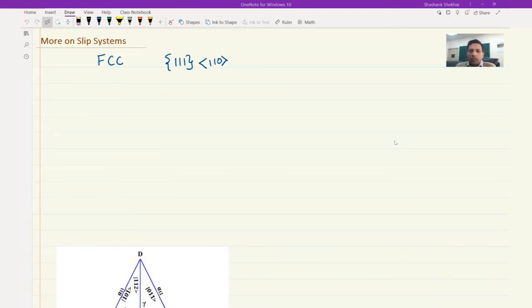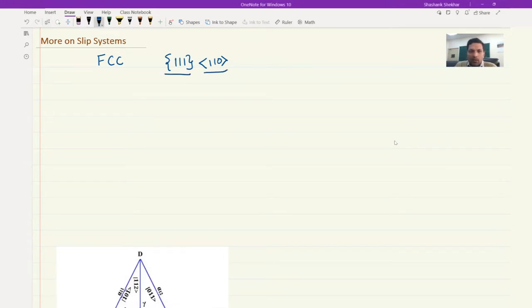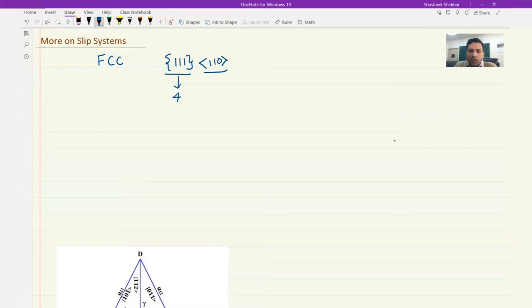We have looked at the various slip systems, now it's time to get familiarized with them. First, let's look at FCC. For FCC, this is the slip system where this is the glide plane and this is the slip direction. How many {111} type planes can you find in a cubic material? The answer is four. What about the <110> direction? If you look closely, there are actually six different variations of the 110 direction.